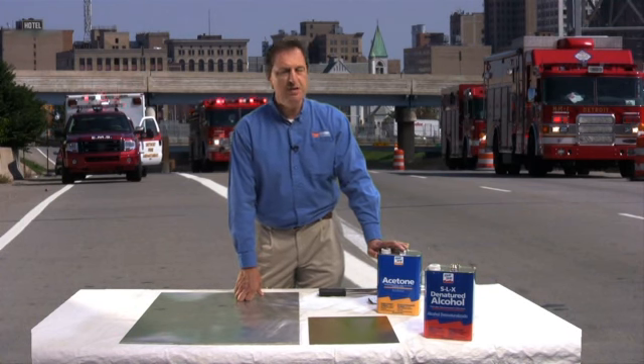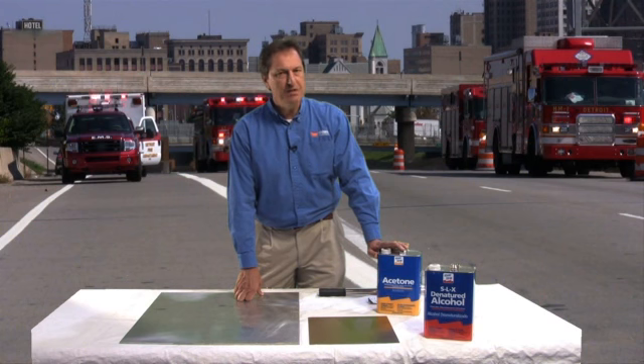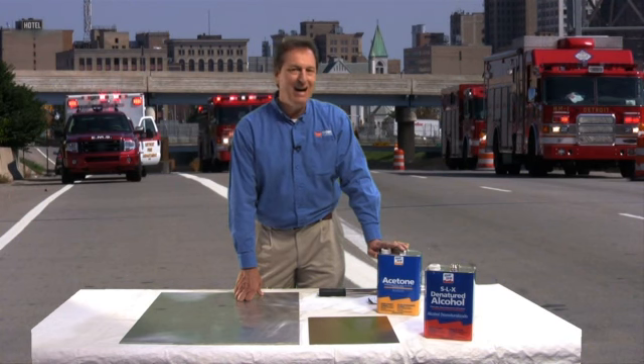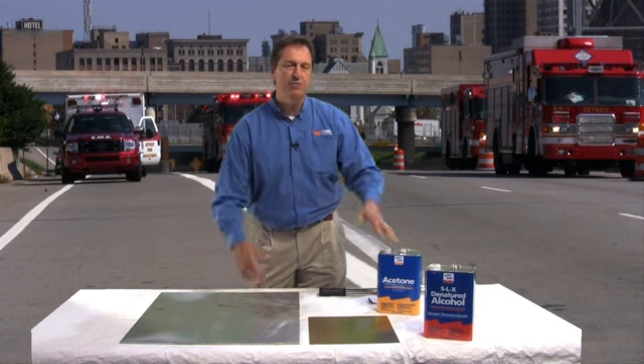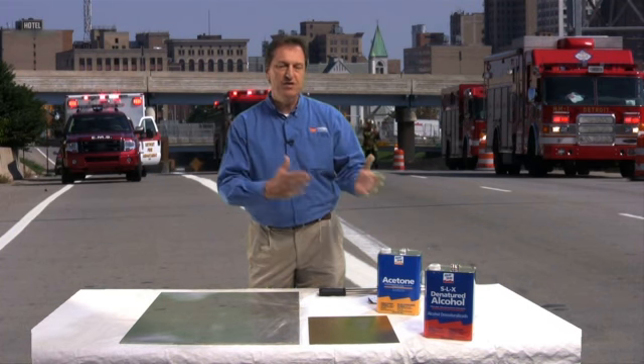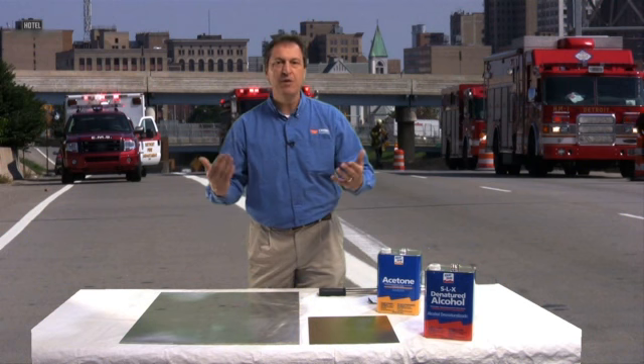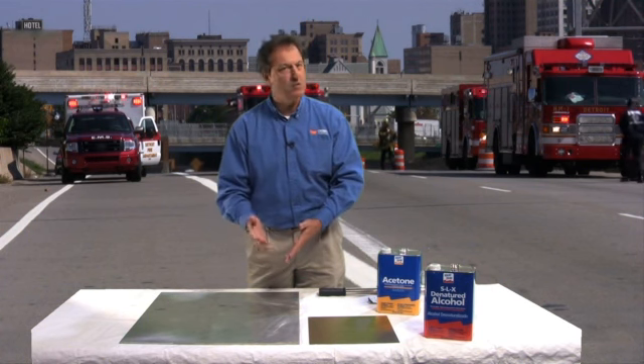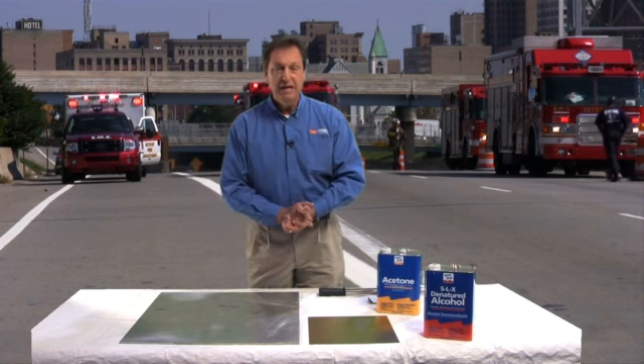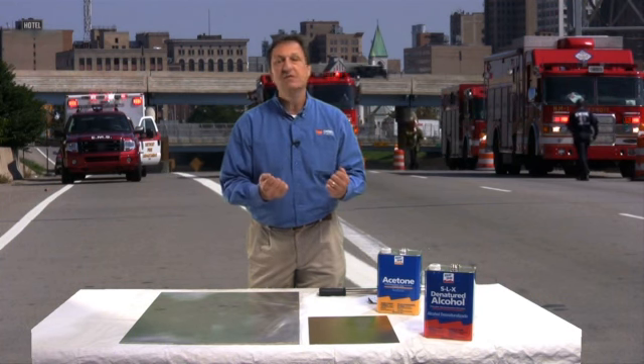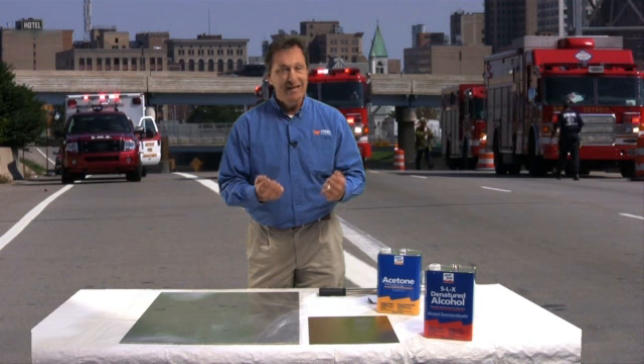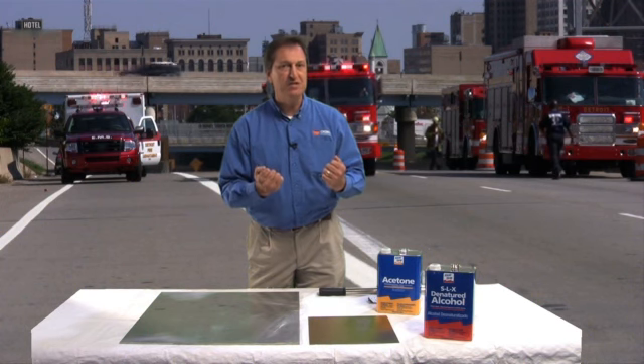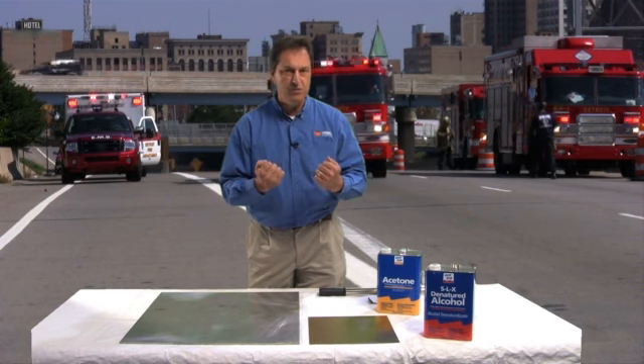Now, one of the areas that we have seen sometimes an issue with has been an oxidized aluminum. We actually ran into a situation with a manufacturer of fire trucks where they stored their aluminum outside, and when they went to apply our product, the product was not sticking very well. The reason is that oxide really lowers the surface energy of that substrate, and now all of a sudden the pressure sensitive systems aren't going to want to lock on as well.